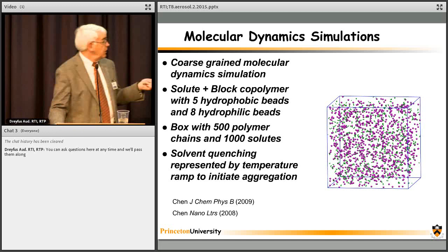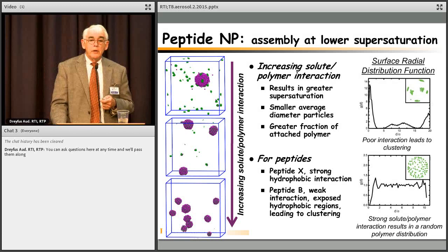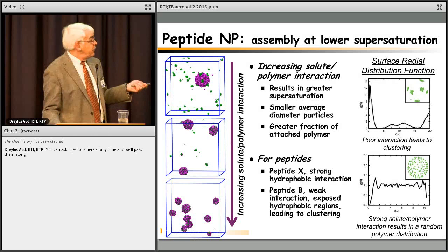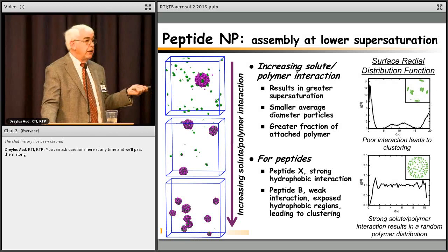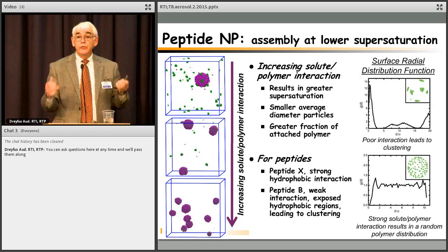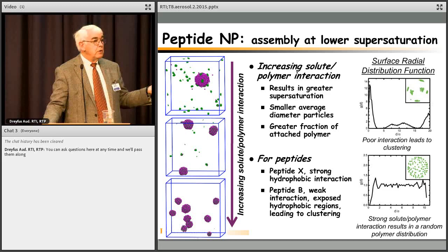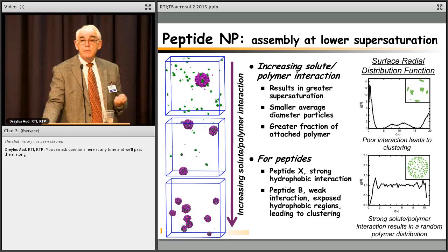What you find in that simulation, and what explains what we see in the population of those particles, is that if the binding energy is very high between the hydrophobic block of the polymer and the solute, then the particle is well covered by these PEG chains, so it's well stabilized. And if you do the radial distribution function, that is the spacing between the hydrophobic blocks on this nanoparticle surface, you can see it's much flatter. It's the same everywhere. So that makes a nice stable particle.